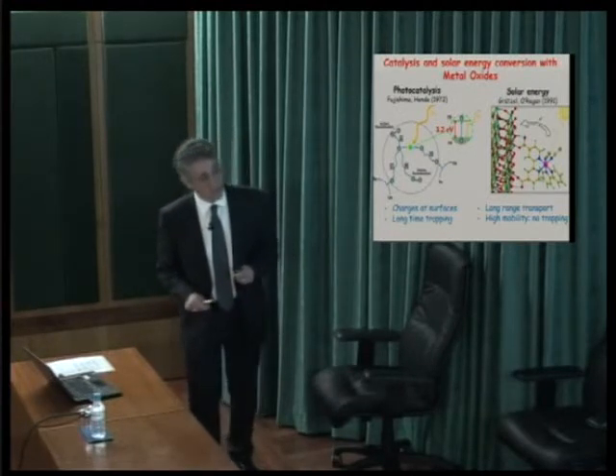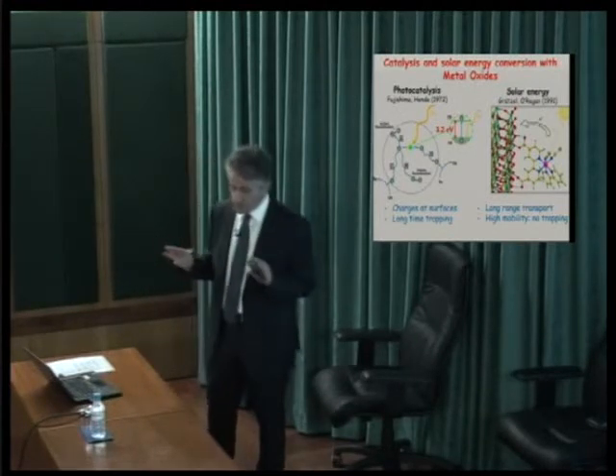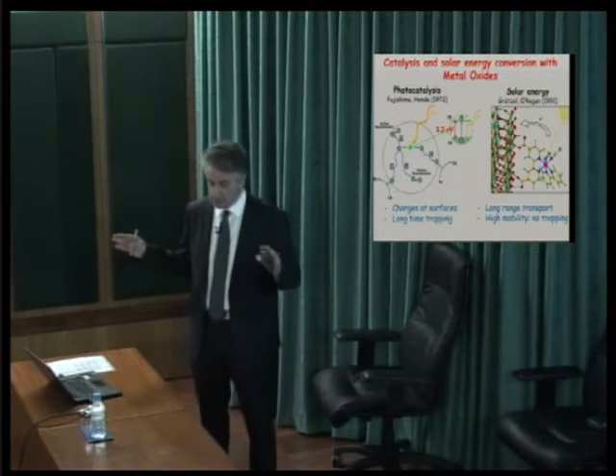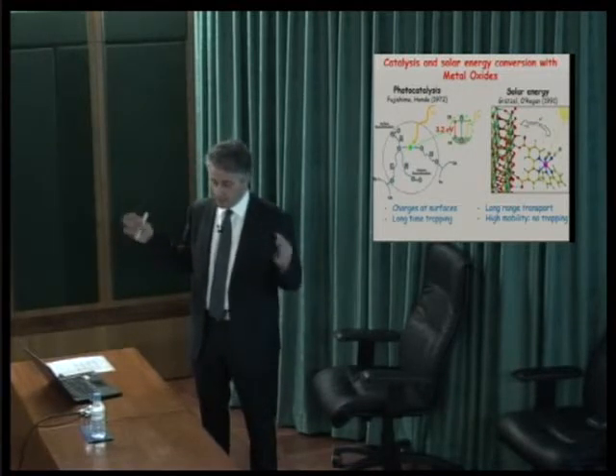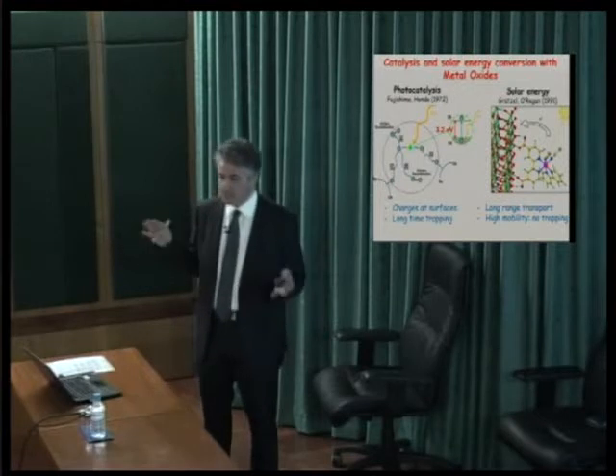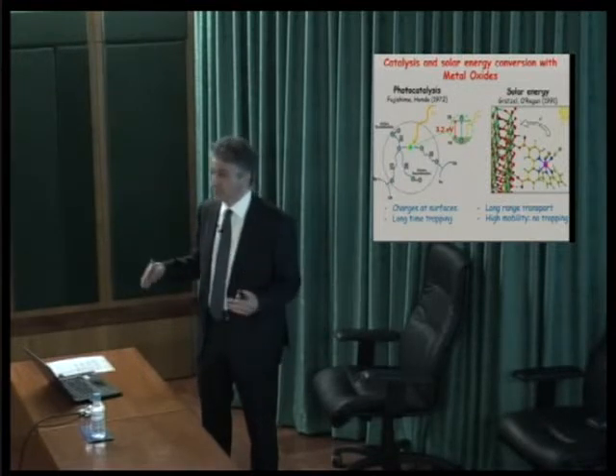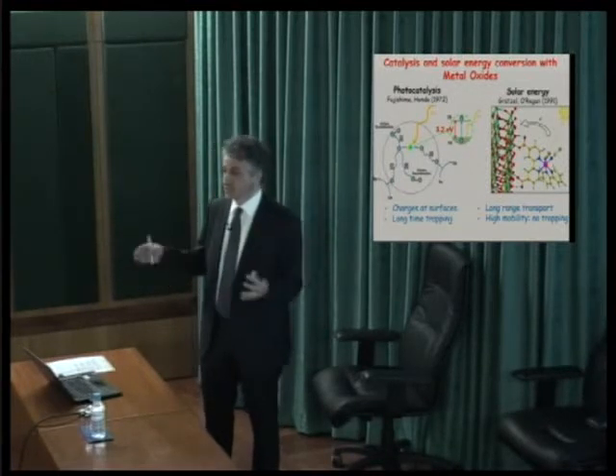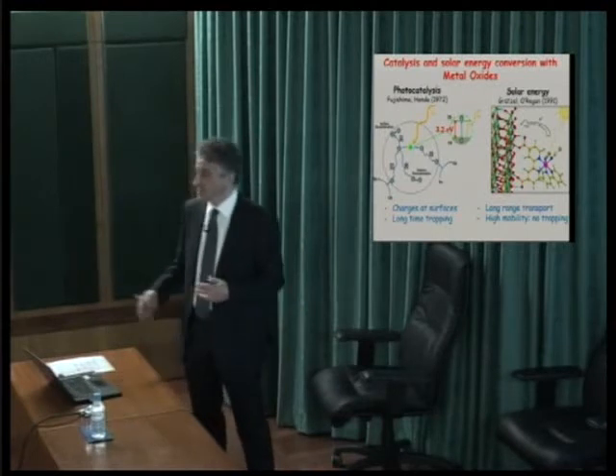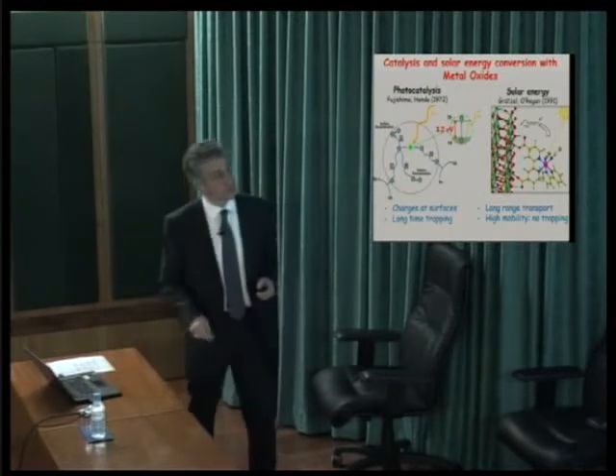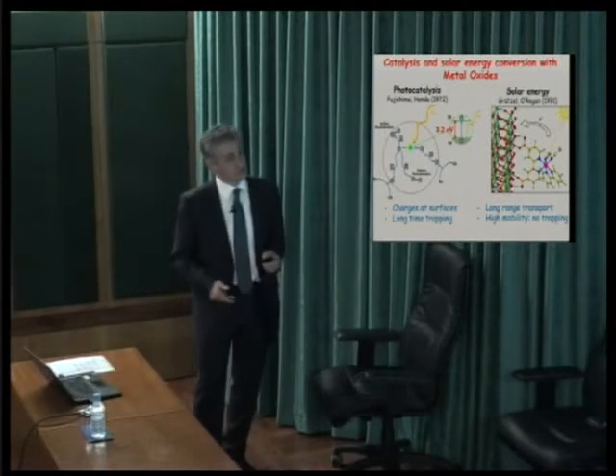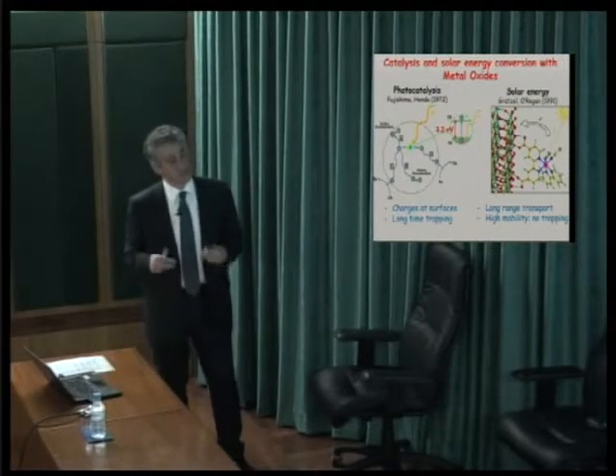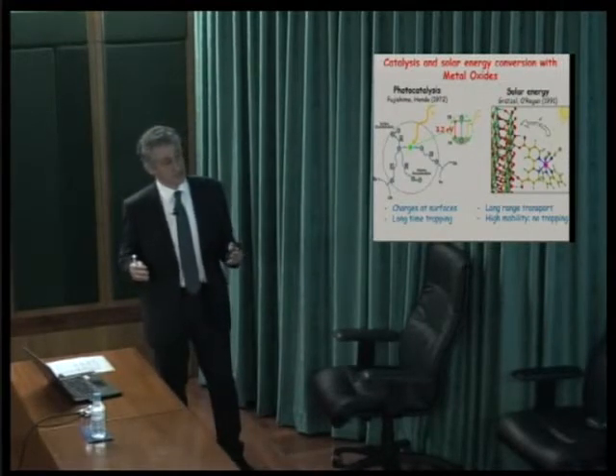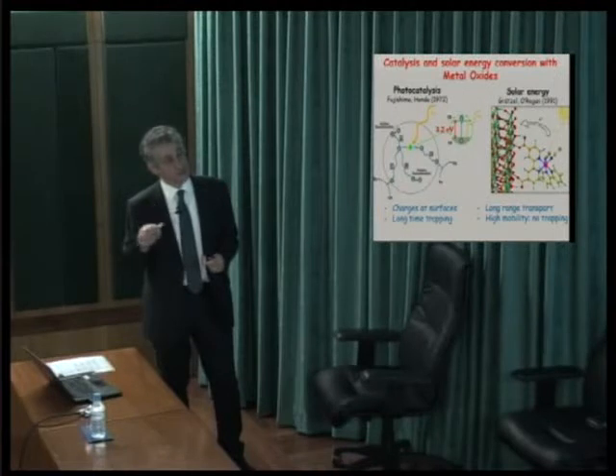So there were many studies done with infrared, visible, terahertz probes of the charge carrier dynamics in these systems. But when you're doing probes in these wavelengths, what you see are free charges in the conduction band. And these free charges are not specific to the material. Any material would have free charges. I mean, a metal or a semiconductor that you excite to the conduction band will have free charges. And these free charges are described by the Drude model. What we wanted is to see what happens to the charge with element selectivity.